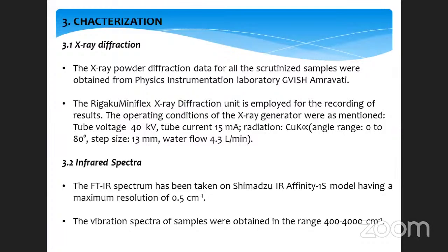The characterization of these composites is made with the help of XRD and IR. The X-ray diffraction technique is used with a Rigaku MiniFlex X-ray diffractometer, and the conditions are maintained with Cu K-alpha rays over an angle of 0 to 80 degrees, with a step size, and water flow maintained at 4.3 liters per minute. Infrared spectra are obtained with the help of a Shimadzu IRAffinity. Next, please.